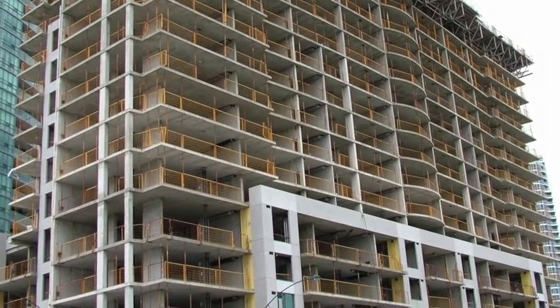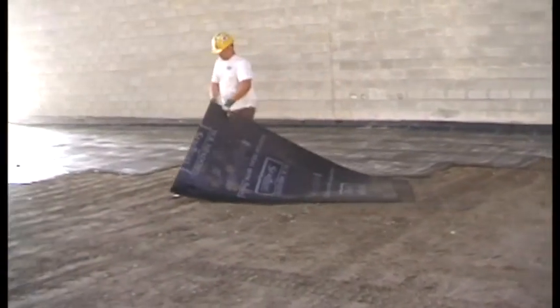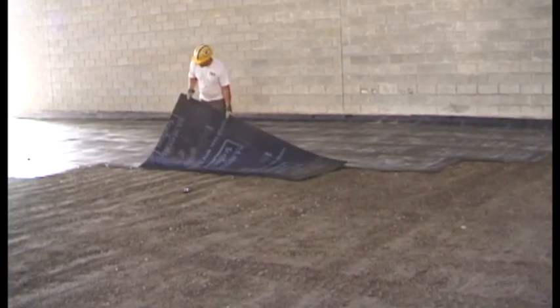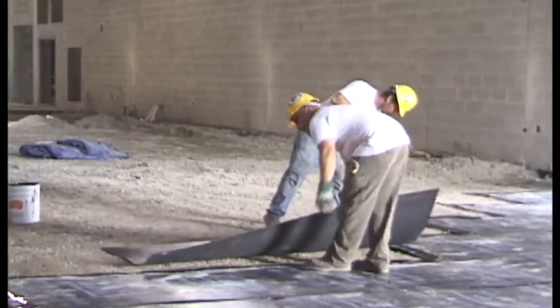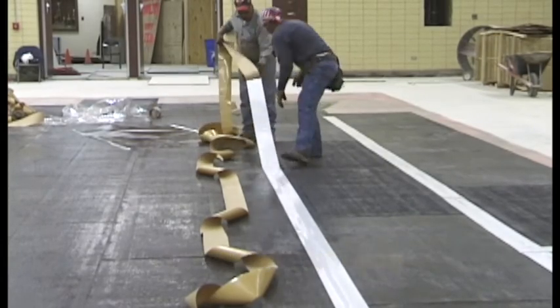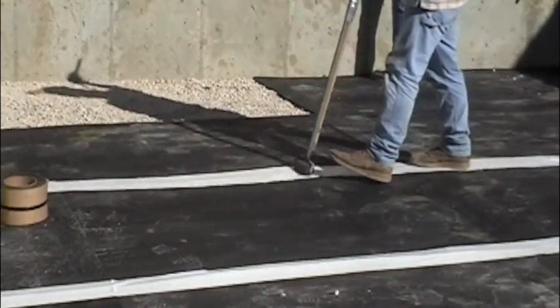This helps prevent damage to lower floor levels. PMPC can be applied directly over tamped grade because it does not require a gravel bed, a bed of sand, and/or crusher rock before the installation of the floor slab, although these practices are acceptable. Material is placed in position by the butt joint method with joints sealed with PMPC tape poly-side up. Center the PMPC tape over the butt joints and roll down with pressure for a positive seal.